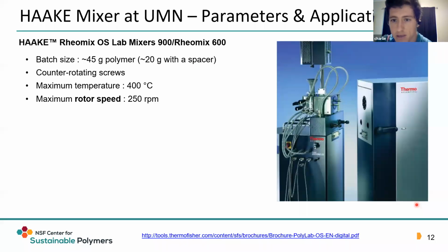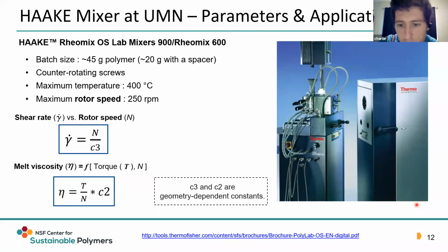This specific Hake mixer we have at the U of M is a Hake ReoMix OS Lab Mixer 900. The batch size is about 45 grams, or you can do a smaller batch size about 20 grams with a spacer. You can do in situ measurements while mixing, such as the shear rate, which is proportional to the rotor speed, and the melt viscosity, which can be measured from the torque and rotor speed.